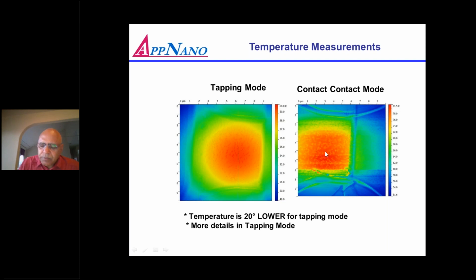When it's in contact mode, you are continuously scanning on the sample, so that is making the thermal gradient disturbed by the heat dissipation from the sample to the tip and through the metal lines. So you can see the heated surface. The good part is you can measure the actual temperature, and in this case the temperature is 20 degrees higher than the tapping mode. So if you want to see the gradient, then tapping mode is better, but if you want to measure the actual temperature, then contact mode is better. For thermal conductivity contrast mode, contact mode is far better because you want to allow the heat to dissipate from the thermocouple to the drain. So these are two different modes.